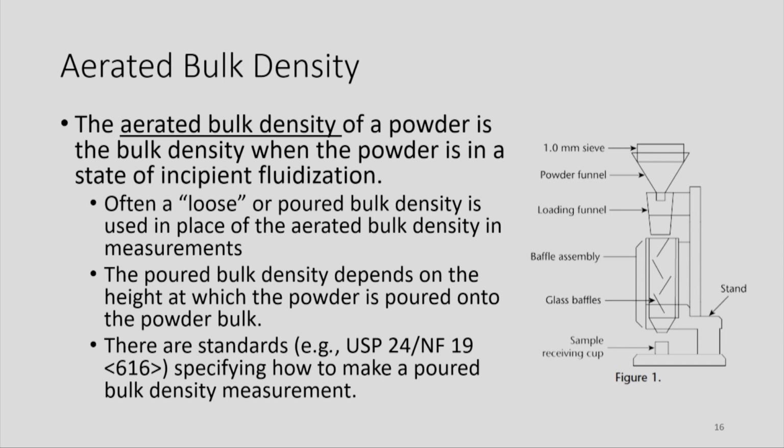Bulk density, you might know, depends on the height from which it flows down, right? If it's too high, there will be chances of fluidization and you might lose some powder. But if the height is too low, there will still be some agglomerates containing some bonding between the particles that affects the volume calculation.